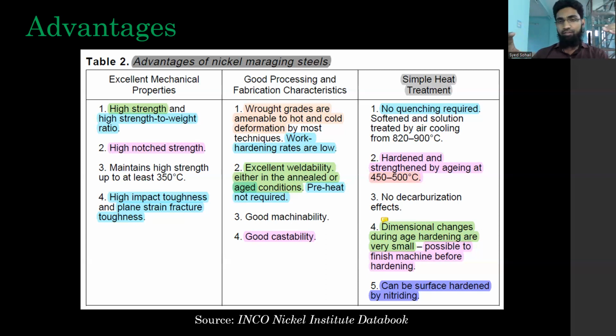Another thing with this dimension change advantage is that it is possible to finish machine before hardening. If you want to finish machining in the sense of dimensions, we have kept tolerances, and from the application perspective, the design specifications are set. So these can be met even in the before aging stage. Because once it is aged, generally after heat treatment, many materials will distort.